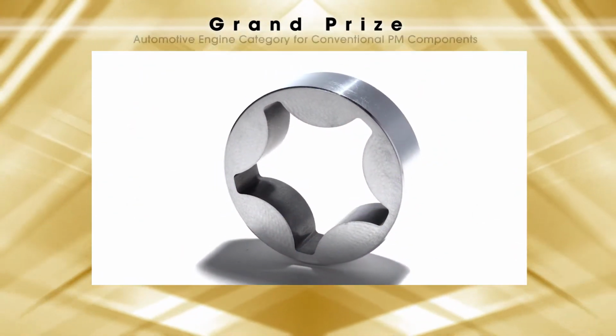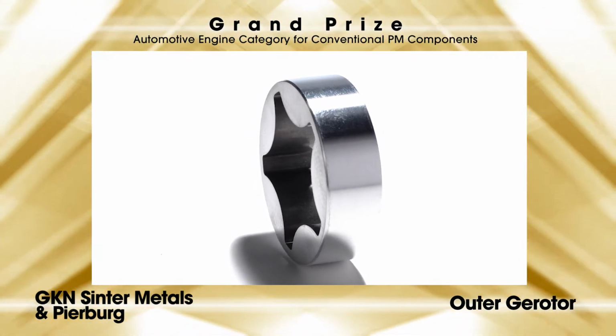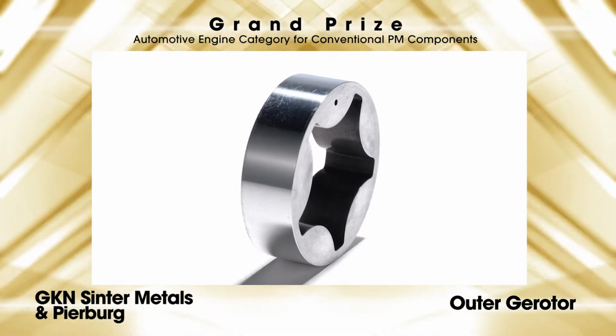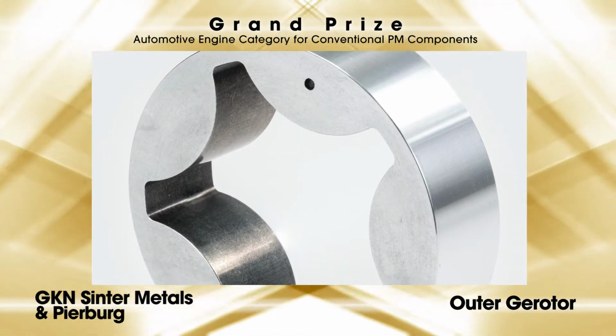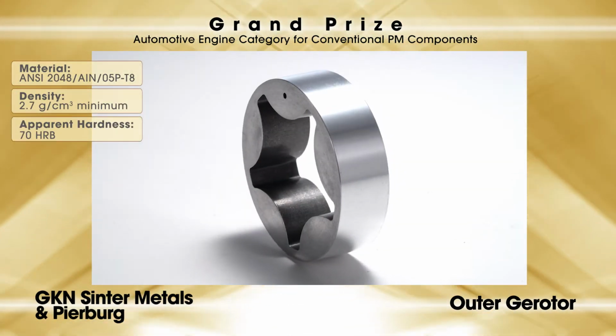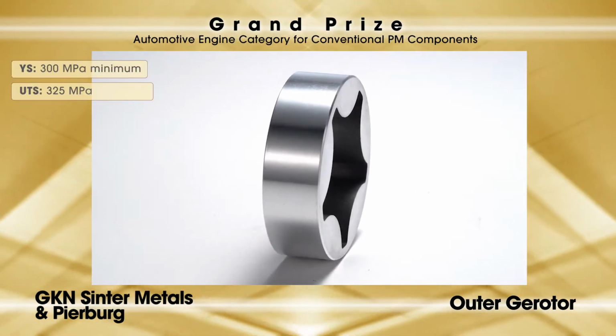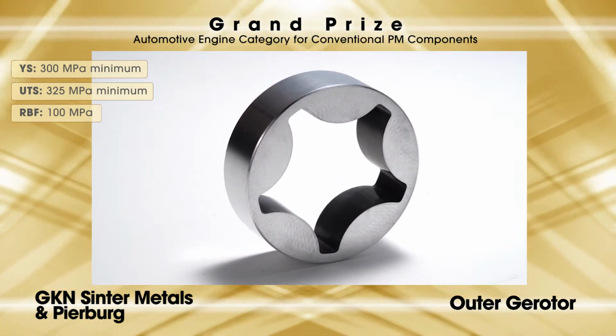GKN Sinter Metals and customer Pierburg received a grand prize in the automotive engine category for conventional PM components for an outer Gerotor. This dry sump pump outer Gerotor for an Italian luxury sports car is made from a metal matrix composite aluminum alloy that contains aluminum nitride ceramic particle reinforcement with an apparent hardness of 70 HRB, a tensile strength of 325 megapascals, and a rotating beam fatigue strength of 100 megapascals.